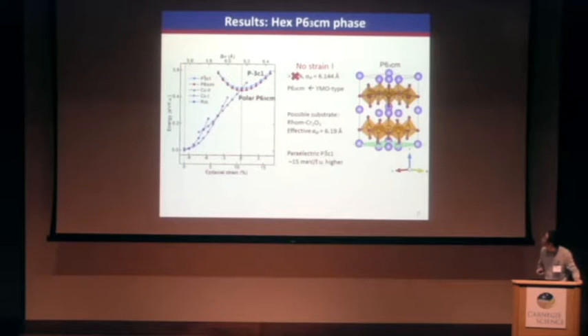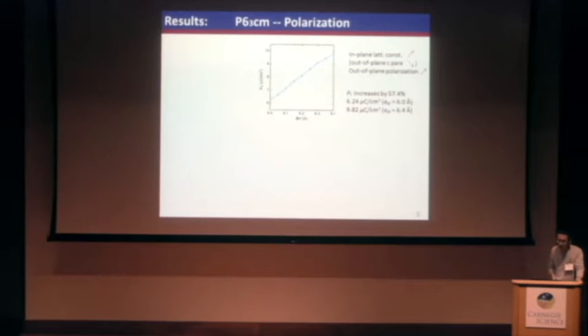And we also look at the paraelectric P-3c1 phase. It is always 15 meV per formula unit higher than the polar P63cm phase. We now look at the polarization of this polar phase. As we can see, when the in-plane lattice constant increases, the polarization increases. We should note that for this phase, the polarization is purely along the c direction.